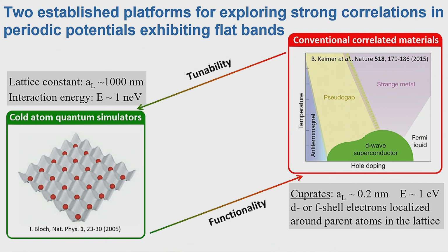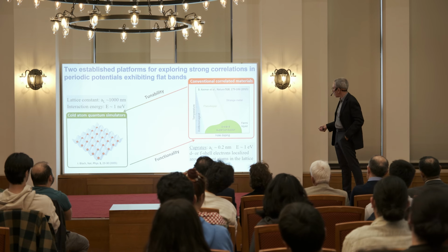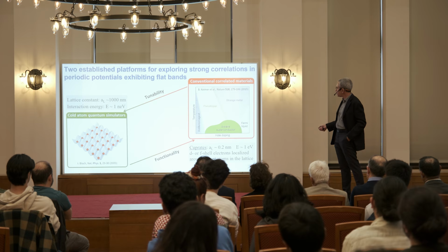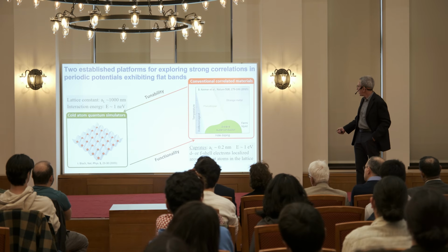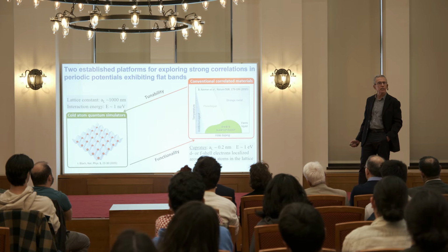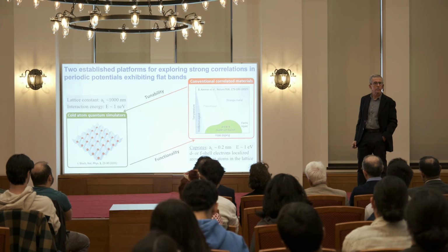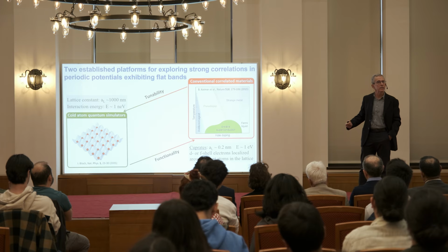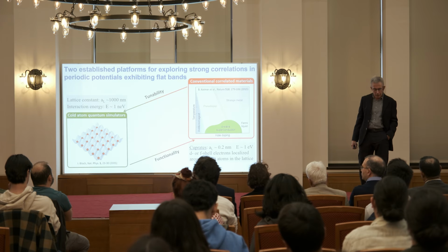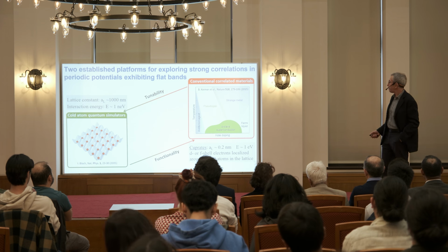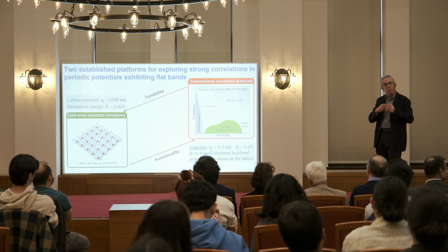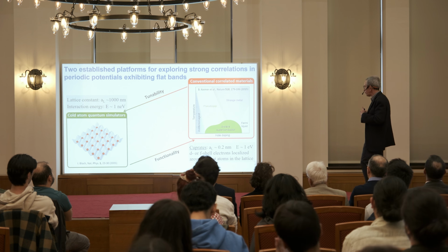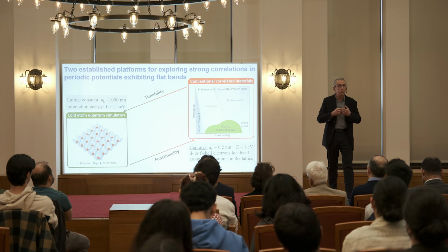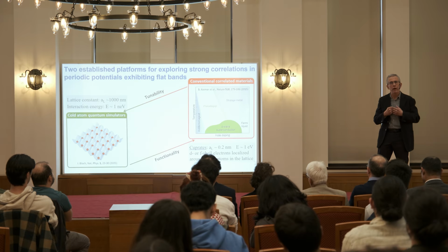So all the spins are arranged in opposite directions, the neighboring spins are arranged in opposite directions. And the interesting things happen as you start doping. Then you get this d-wave superconducting dome, which can have a critical temperature that is on the order of 100 Kelvin. And this, when discovered in '86, created an enormous interest because it looked like there was a jump in critical temperature by almost an order of magnitude, and there was the hope that this can be pushed all the way up to room temperature.